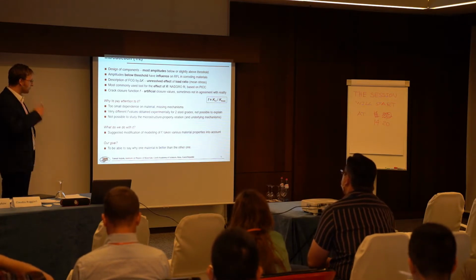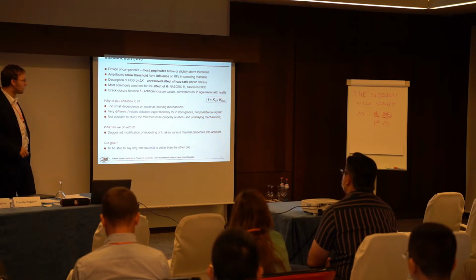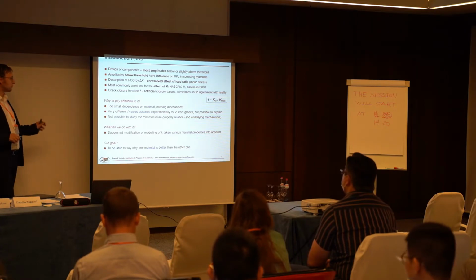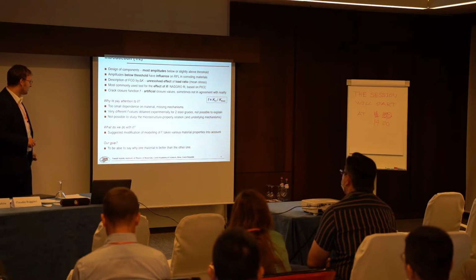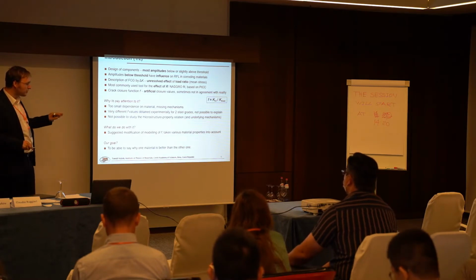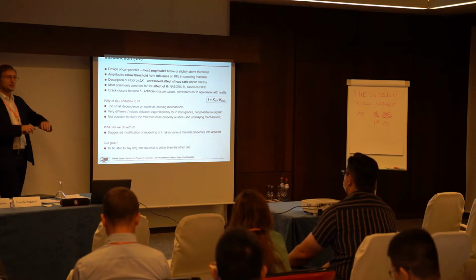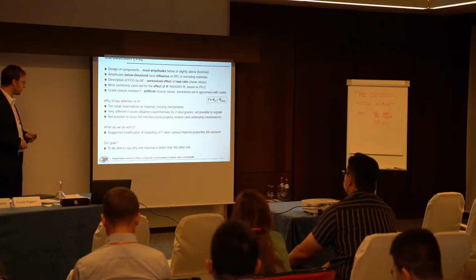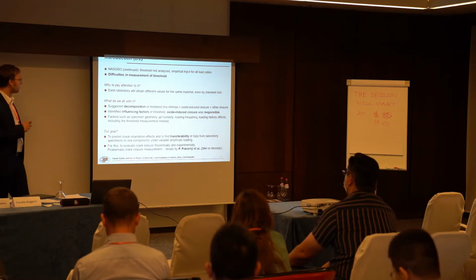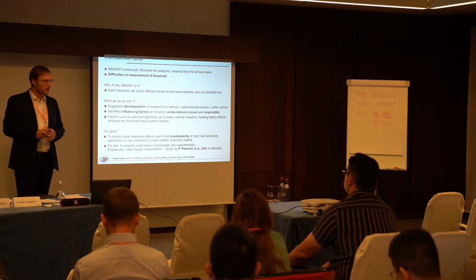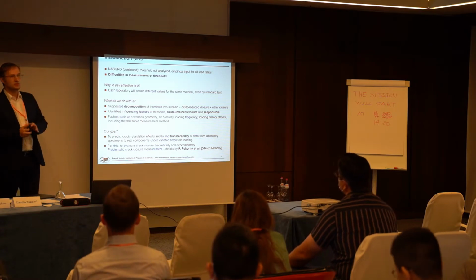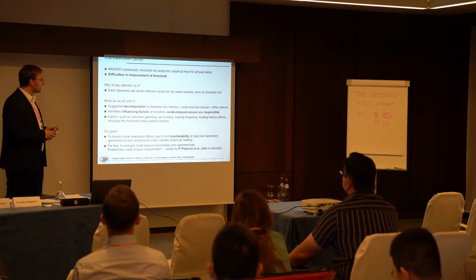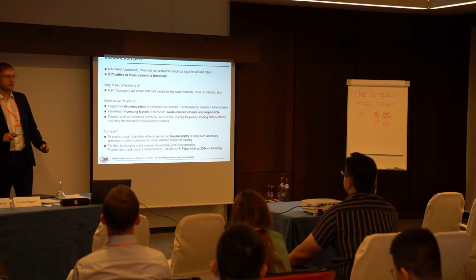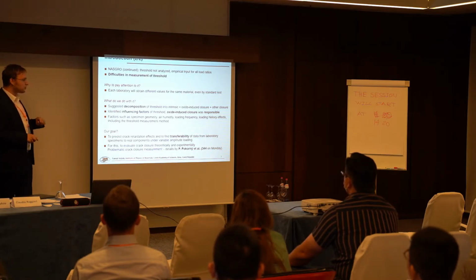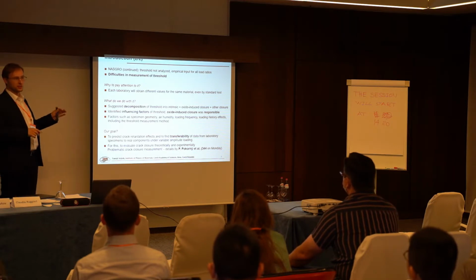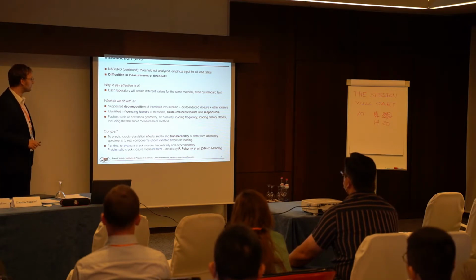So we have probably some missing mechanism or description which would depend on material. And in order to be able to say something about the differences between materials, we need to understand more the mechanisms. This was the part connected to plasticity induced crack closure, but also we have the threshold regime. And in that case, we have other components of crack closure, and also we have some difficulties in measurement of threshold. So the second part of the talk will be focused on it.